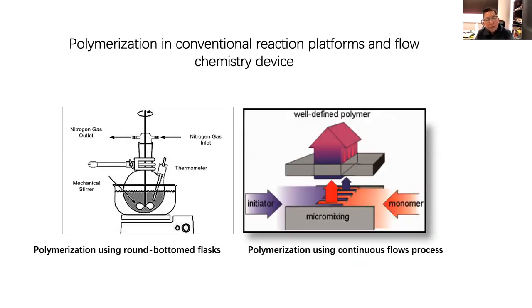Now let's turn more towards polymerization in a conventional reaction platform. Again, most of the examples I've shown you, even on our work, were done under batch reactions. So the figure on the left is relevant and is a very common implement in our lab and in many labs all over. Now, the confinement of a reaction in a very small volume may involve micromixing, but what one wants to achieve is where the initiator and the monomer ratio is controlled in a very small space. In doing so, you have a very efficient distribution of heat or catalysis. And in other words, the collision theory is pretty much controlled in an environment like micromixing or even a confined continuous flow environment, resulting in a well-defined polymer.